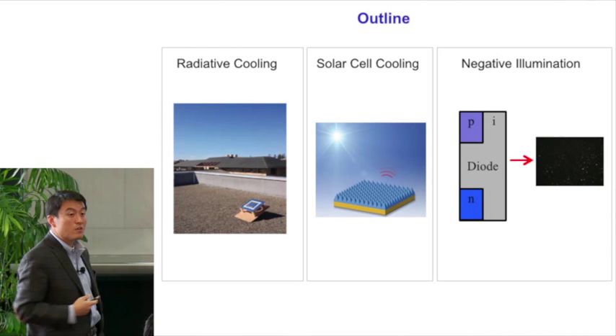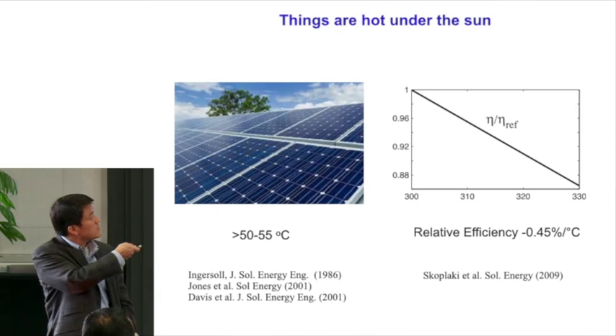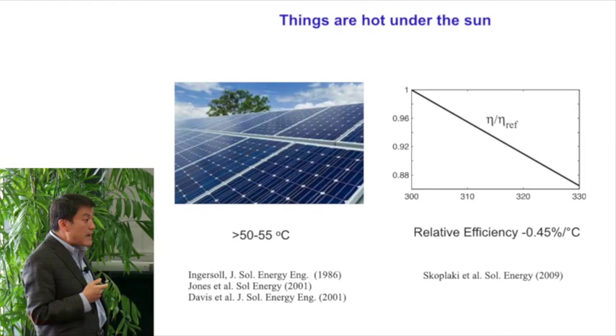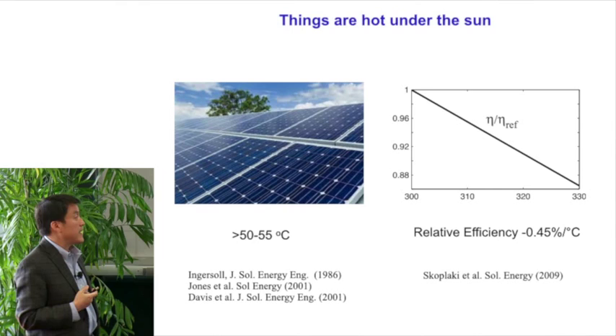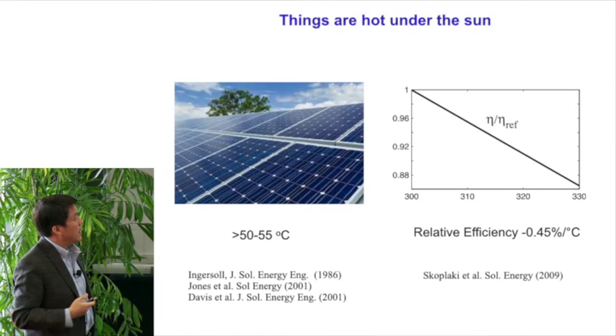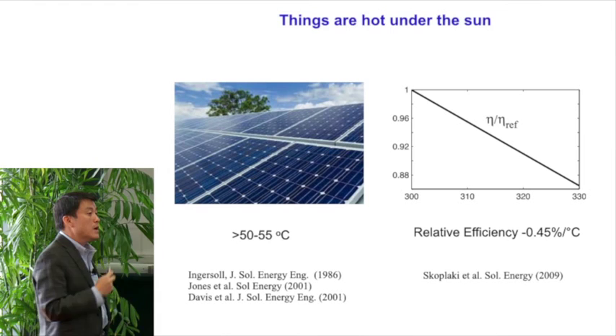A solar cell, of course, does not sit in a solar simulator. It has to go up on the roof. And as a result, it is going to heat up very substantially. A typical operating temperature of a solar cell can be as high as 50 to 55 degrees Celsius. And this has a very severe efficiency penalty, as well as a lifetime penalty. So being able to develop a technique to cool solar cells is extremely important.